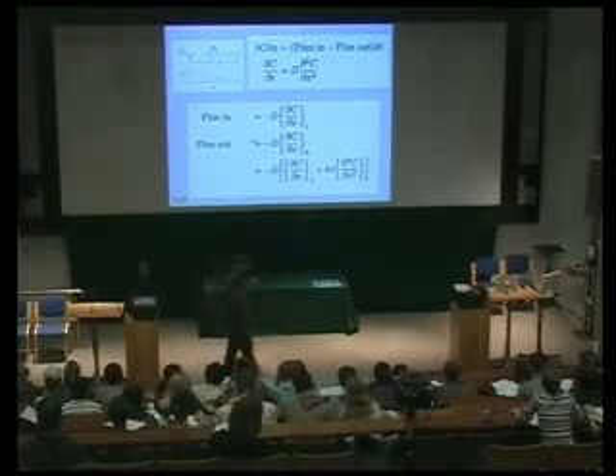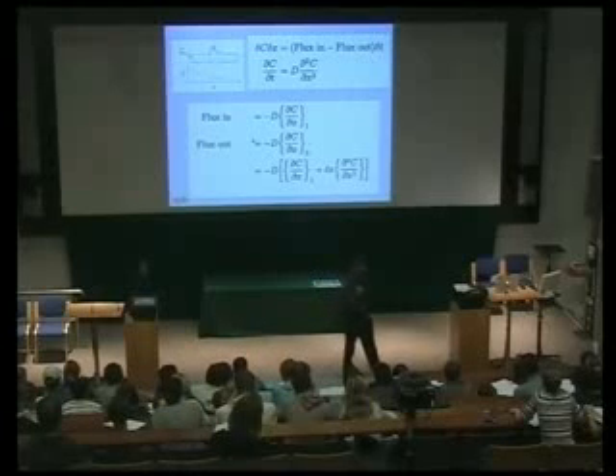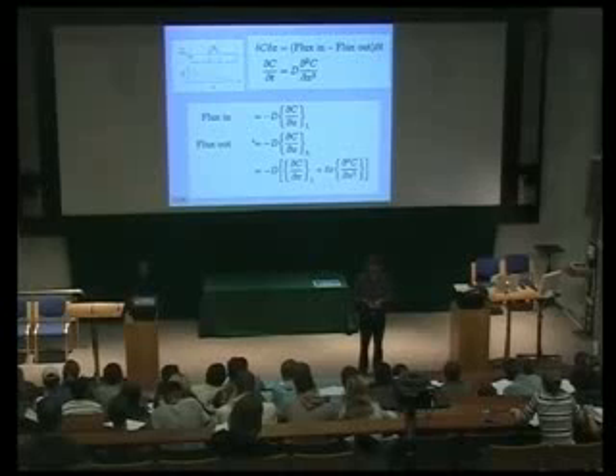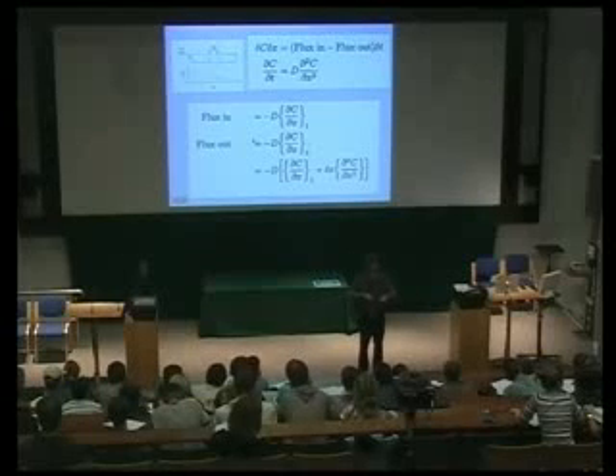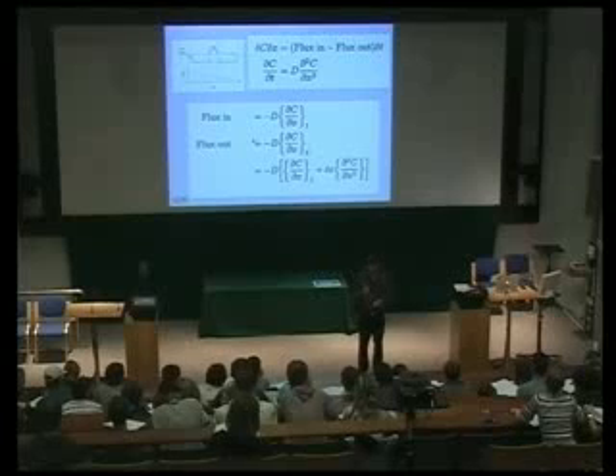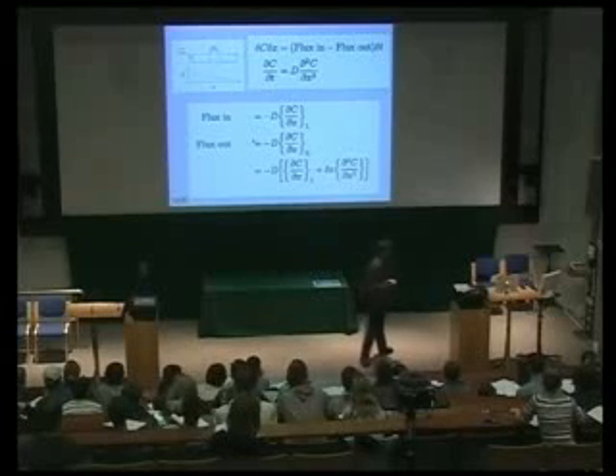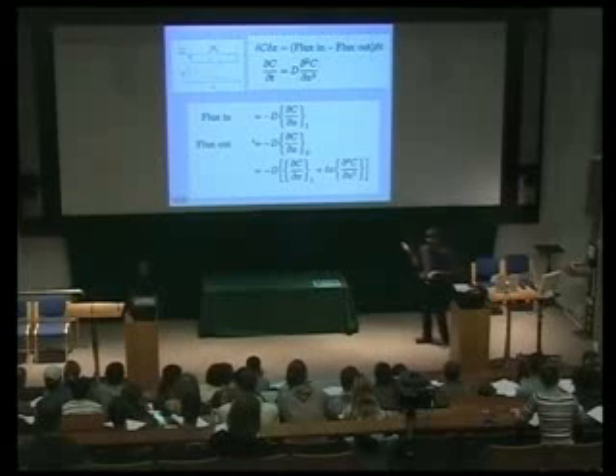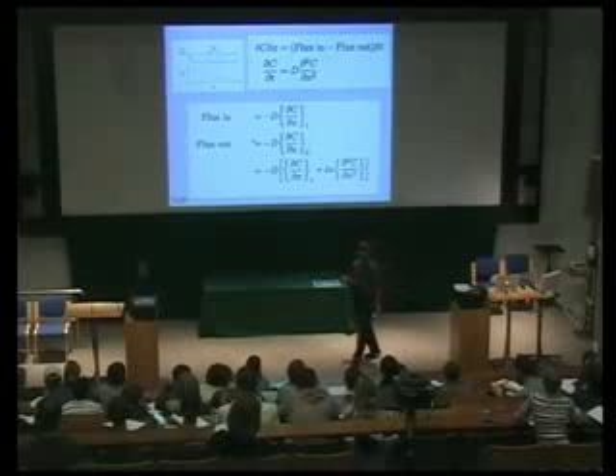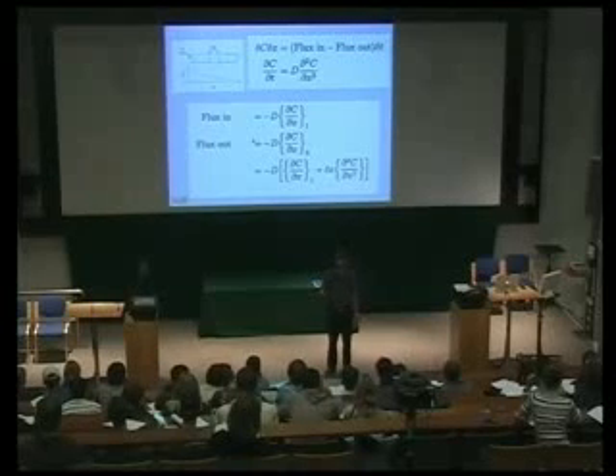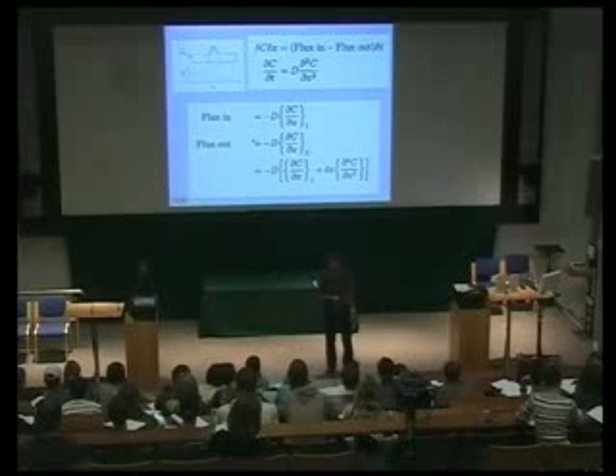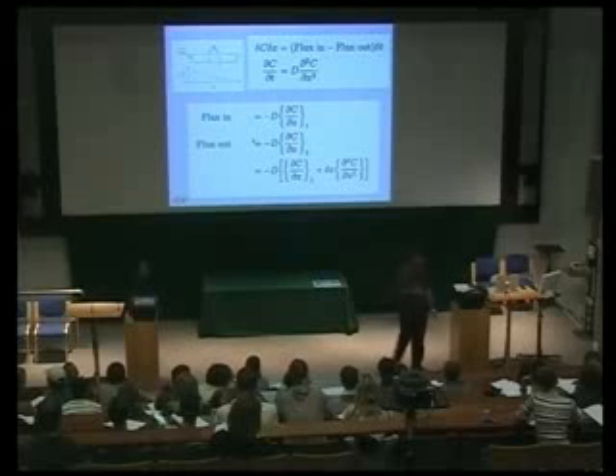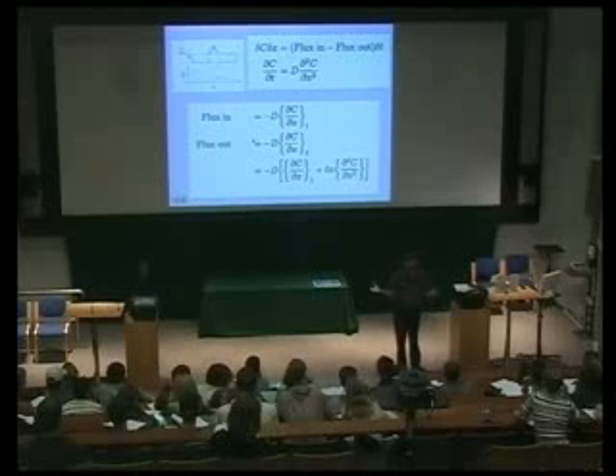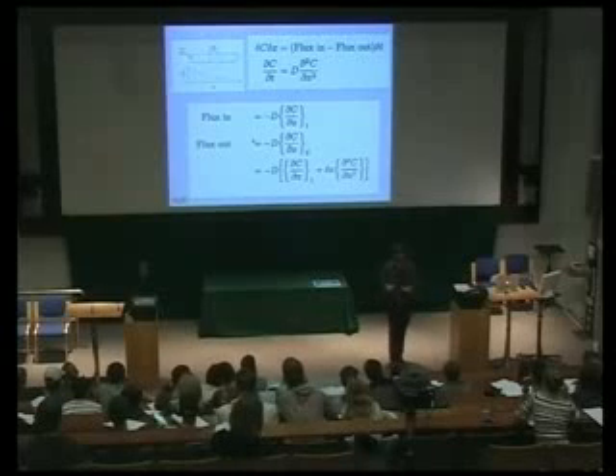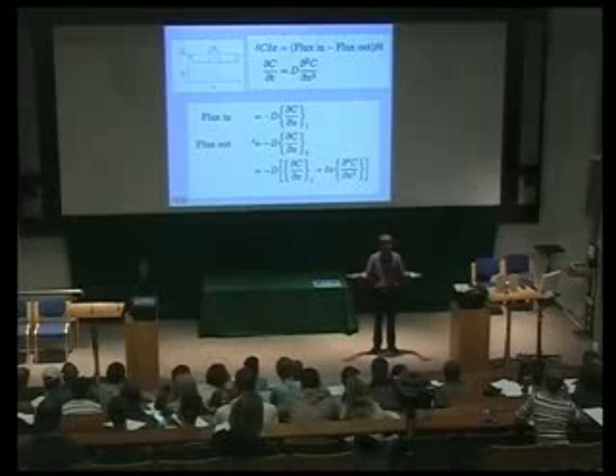And really, with those two equations, you can deal with 99% of all cases where we have diffusion happening. So for example, if you're doping semiconductors, or you're introducing certain species of atoms into the surface of a metal, these equations serve extremely well. But again, you see, Fick's second law relies on the assumption that the flux varies with the gradient of concentration. Okay? You might think that really it should vary with the gradient of free energy, because free energy is what determines equilibrium. Yeah? The reason why diffusion really happens is that it's trying to make the free energy uniform everywhere.